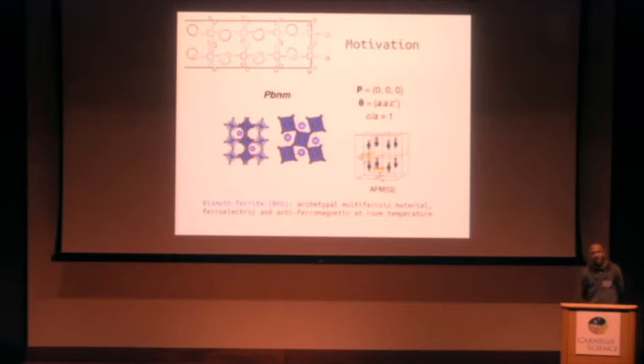So in bismuth ferrite, there is a competition between this ferroelectric and magnetic phase and an orthorhombic non-polar phase, Pbnm. So when you heat bismuth ferrite at ambient pressure conditions, at some point it becomes paraelectric and adopts this phase. Or if you keep a constant temperature and compress it under pressure, also at some point it stabilizes in this non-polar phase, right? The magnetic order in this case is also antiferromagnetic order G, the same that we found in the ground state. And we find a somewhat different pattern of oxygen octahedral rotations, right?